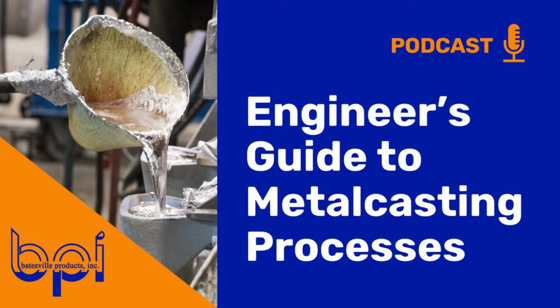In permanent mold, they typically use a steel mold to develop the actual mold, the fixture they pour into, and that really develops permanent mold casting capabilities and tolerances across the life of that part. In die casting, where you see a little bit different too, is again they're forcing it in there. So you have a lot of that same porosity or shrinkage possibilities that you would see in sand casting as well.